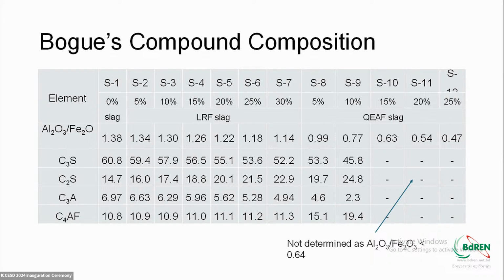Now, if we calculated the bogue compounds - belite, alite, and aluminite - of cement, for LRF slag they were all within permissible limits. But for QEAF slag, the ferrite aluminite percentage was so low that ultimately other compounds could not be determined, because the formula we used required that the aluminite ferrite percentage must be greater than 64%.